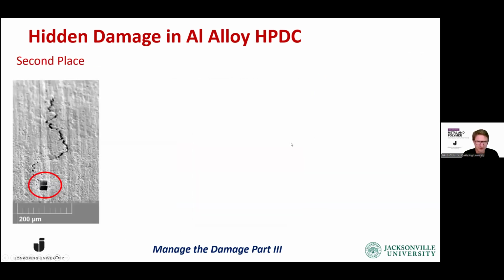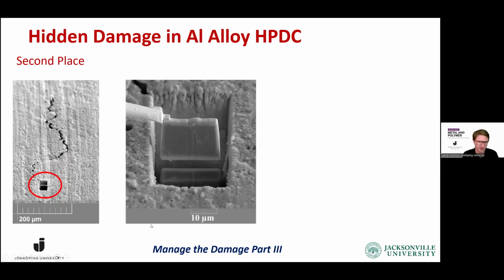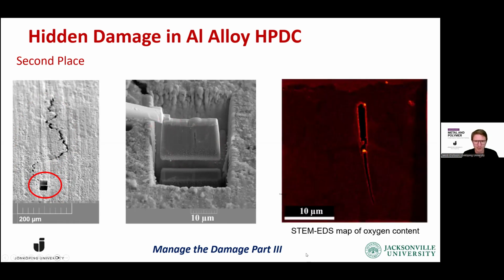If we want to take a look at the second place position, we could see already in the paint on the DIC samples that there was a crack forming, but when we remove the paint, you can see in the SEM picture here that there's a big crack, and we can then use focused ion beam technology to make a small cutout from the front tip of this crack. So you see we're taking a very small sample. You see the scale down there, it's 10 micrometers. So it's a very small sample that we can then lift up and do a STEM EDS map of the chemical composition to see what we have here.